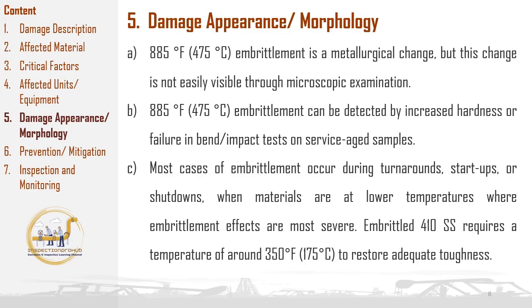In addition to hardness tests, bend or impact tests on service-aged samples often demonstrate reduced capacity to resist deformation or absorb energy, leading to failure. These tests are essential for identifying materials prone to embrittlement, helping ensure the reliability and integrity of components exposed to high temperatures in industrial settings.